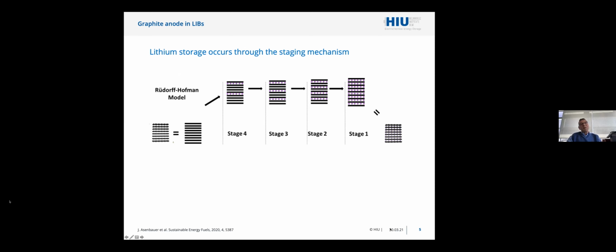There was a mechanism proposed by Rüdorff and Hofmann in which practically they proposed that layers were filled, and then at a certain point another layer was filled, as you can see in this sketch here. Nonetheless, this was obviously a simple picture because it is very tough to believe that at a certain point all the lithium ions could move from this layer to the previous one, going from stage 4 to stage 3, for example, and then the same going to stage 2.